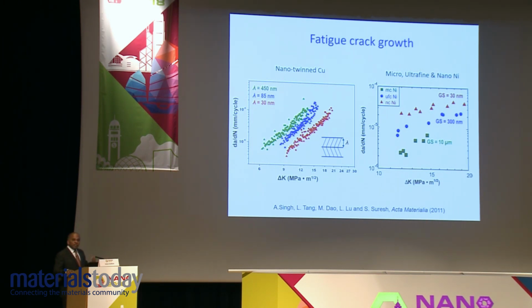So what is beneficial for high cycle fatigue is actually not so good for fatigue crack propagation, especially at low crack propagation rates in the near threshold regime, where conventional coarse grain materials perform much, much better than a nanocrystalline material. We can try to overcome that by tricking the material by introducing initially coherent internal boundaries at the nanoscale, which are also thermally and mechanically stable. And that's what is shown on the left-hand side. So for 3 different nano-twin cases, you have twin spacing of 30 nanometers, 85 nanometers, and 450 nanometers.